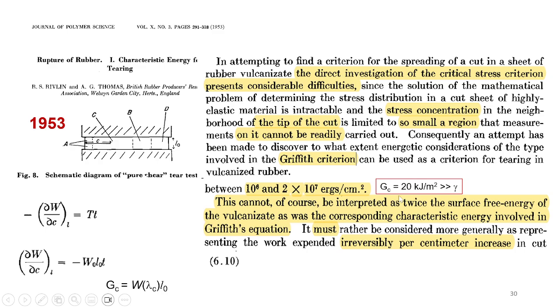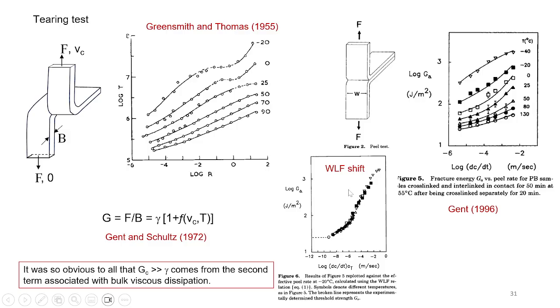higher than surface fracture energy. So I'm just flashing this result again and again, showing you that the so-called energy release rate is higher as you tear faster, and is higher as you go to lower temperature. All this is summarized in terms of this expression, suggesting that there is an additional contribution coming from tearing faster. Because this G is much higher than gamma.